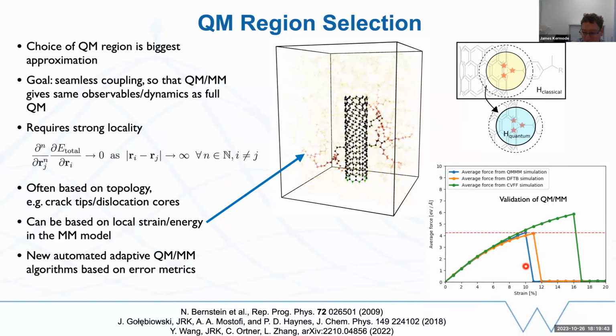We looked at the stress strain curve, essentially, how much we strain and how hard you have to pull in order to remove the nanotube. And then we did the same thing with the classical model alone. You have to pull much harder, as in the simulation I showed earlier on. The classical model overestimates the energy required to break bonds significantly. Whereas if we use this coupled quantum mechanical, molecular mechanical approach, where we treat just these interaction points with quantum mechanics, we vastly reduce the overall cost and we get the same, more or less, overall response.